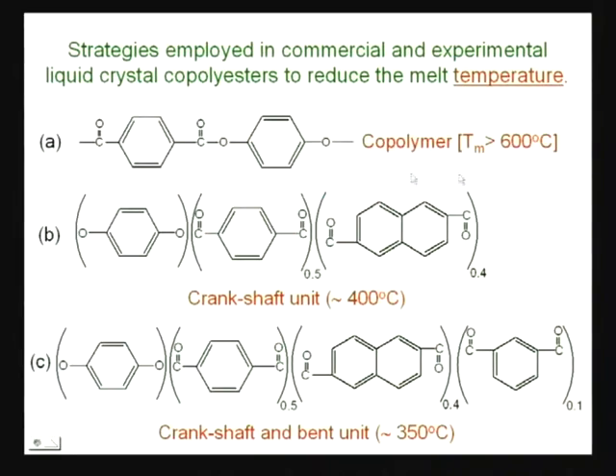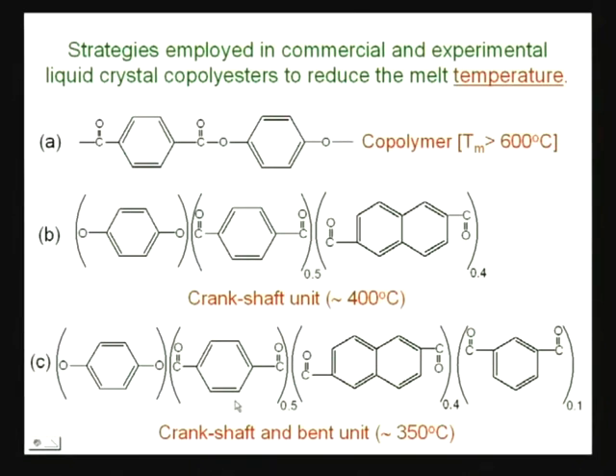So, you can regulate that. Here lies the tailorability of such polymers. You can tailor the melting temperature of such polymers by introducing a small quantity of this monomer or this reactant. Further, you see the temperature can be decreased from 400 to 350 if you incorporate this monomer. You see these units are kept, this is also kept, and again a little bit of this swivel unit, sorry, bent unit, this bent unit, it actually further reduces this temperature to 350 degrees. Okay.